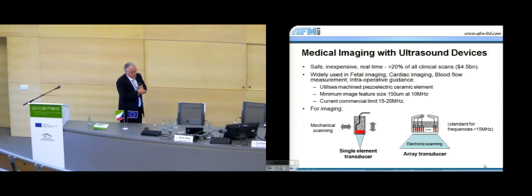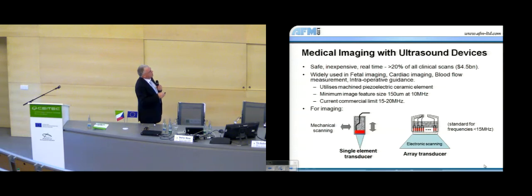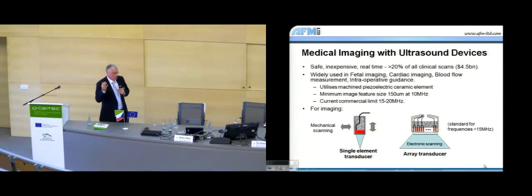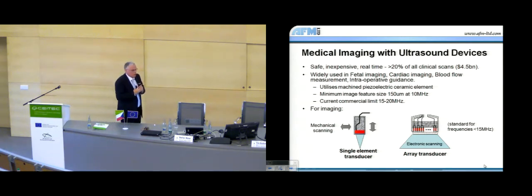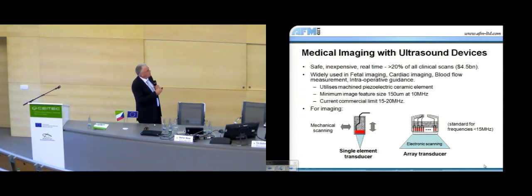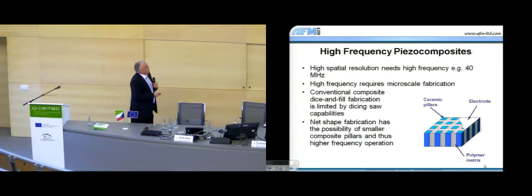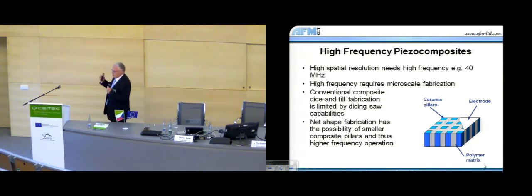A number of different ways one can use the device for making an image. One can use a very simple single element device and then mechanically scan the device across what you're trying to look at to form an image. Or you can use a more complicated array transducer where we do this scanning electronically. And by far, most of the conventional images that are taken nowadays at the lower frequency, 10 megahertz or so, are done by an array transducer. That's the really established technology. What makes that transducer work? What makes the technology work? Well, it comes down to a piece of piezoelectric ceramic again.